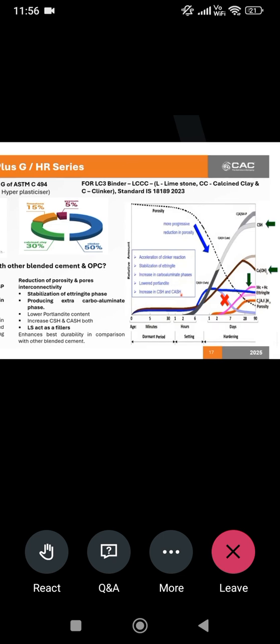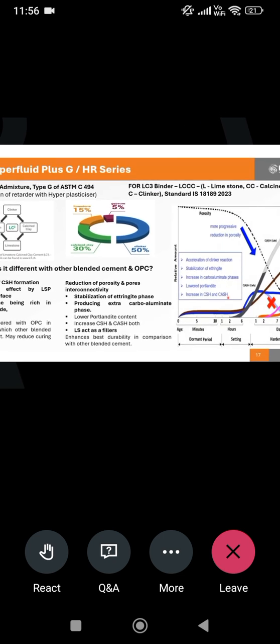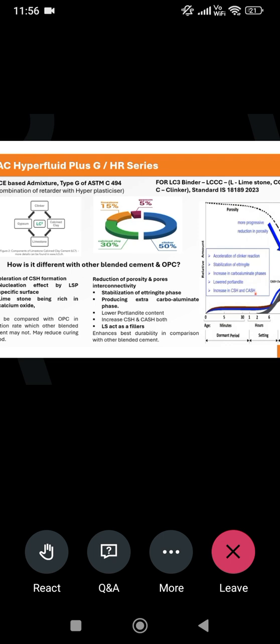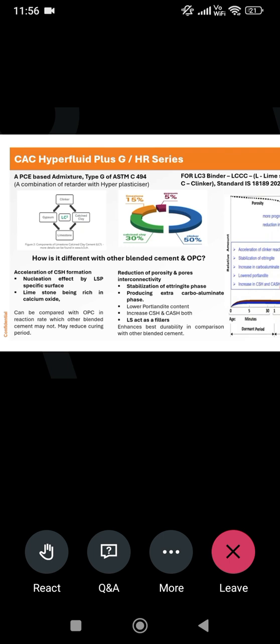What is the nucleation effect? In the presence of limestone, CSH formation from C3A and C3S is faster. That is why the gain of strength is comparable with OPC. In one day it is a little lower, but in 3 days they are equal. So this is the disadvantage of other blended cement. Now it is being compensated. So it is actually nullifying the disadvantage of OPC, that OPC is not very impermeable because calcium hydroxide is not being consumed. Many pores are there. So on one side it is more durable, and it is also having the same rate of gaining strength as compared to OPC. This is first, and it is also less permeable than any of the blended cement. This is the highlight, right?